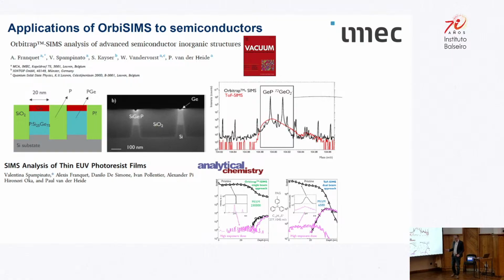Another application that they used it for was in extreme UV lithography. So extreme UV lithography is what they use now to get these 3 nanometer and below resolution, and very, very fancy technologies that they use to do that. And the photoresists have got different chemistries. So they used OrbiSIMS to identify what was happening. With TOF SIMS, the peaks were too blurred. They couldn't identify what was going on. But by switching to OrbiSIMS, they were then able to separate out the chemistry and figure out what was going on.